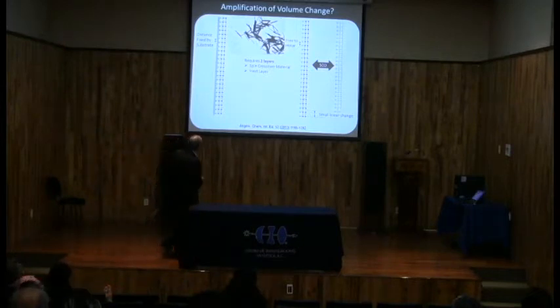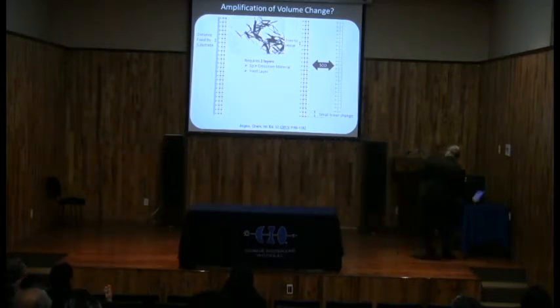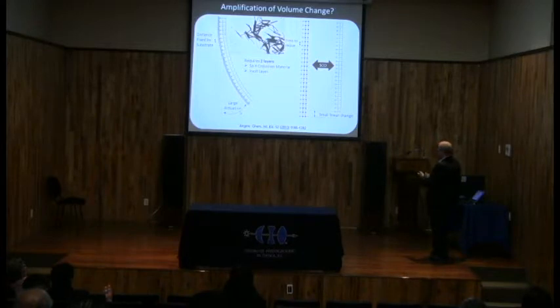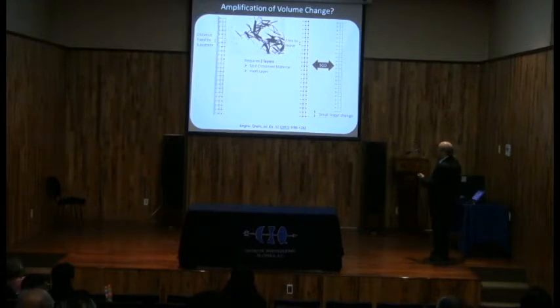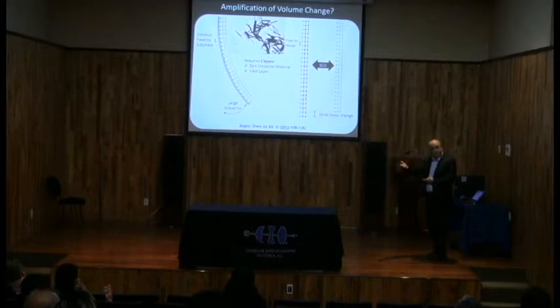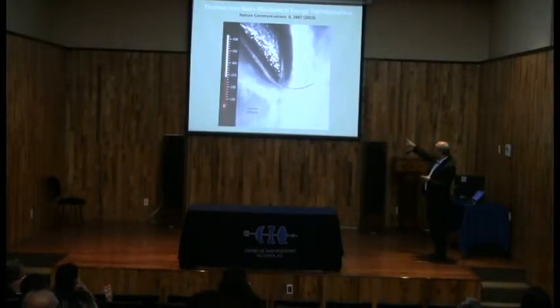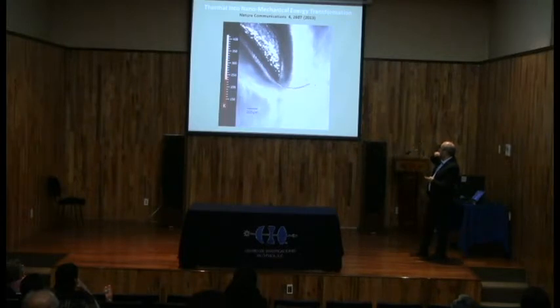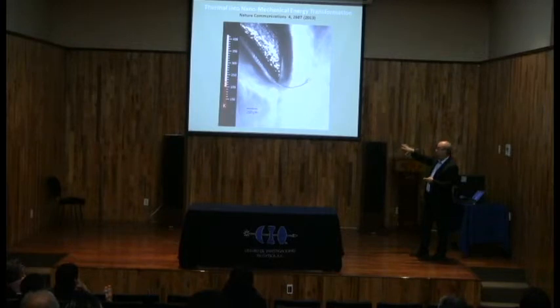Okay? So then on paper, when we have the crossover, we expect to have this. Okay? Because you have a bilayer, one layer wants to change its volume, the other one is constant. So you expect that when you have the crossover to have theoretically this actuation. Okay? So then we did this experiment, as you can see here. We fixed our bilayer on a substrate and we changed the temperature to have the crossover. And you see the actuation follows very well the change of temperature. So then we are converting temperature into mechanical motion.